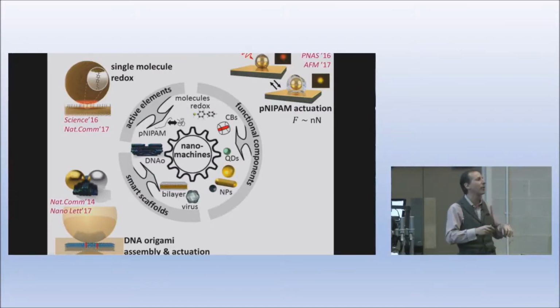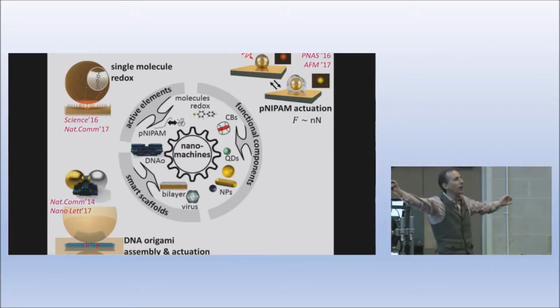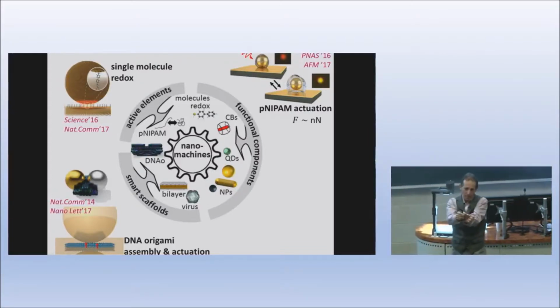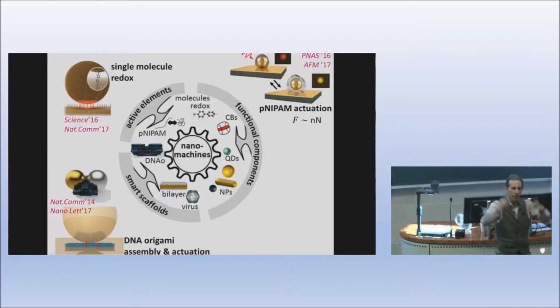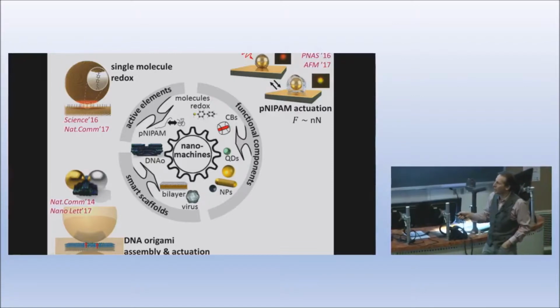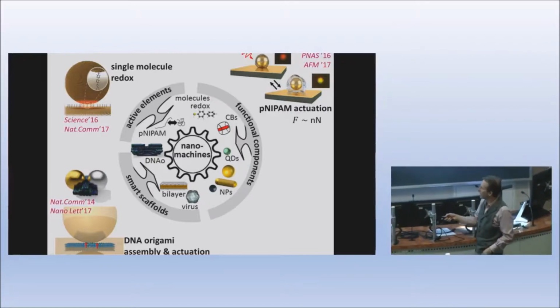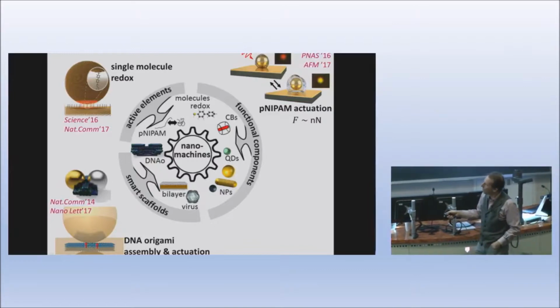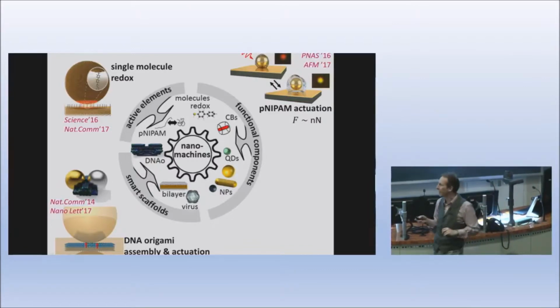It's a wonderful constructional tool. You take a long length of viral DNA and you put in staple strands which staple this bit of the DNA to that bit of the DNA, and it folds up. And if you add 30 strands, you can fold up rigid three-dimensional structures. So you can make, say, an object that looks like that with different materials a few nanometers apart. Or something like this, where we make this nanoparticle mirror structure again, and we put specific molecules in specific locations.